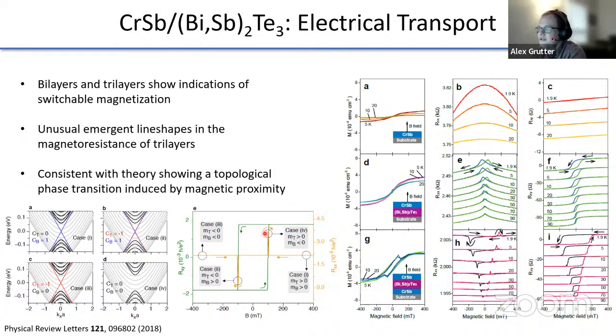We tried hard to carefully look at control measurements, where we look at what the chromium antimonide does on its own, and then compare it to the bilayer. I think the biggest point to make here is that the changes are significant when you start to get these interfaces. But of course, there's been a lot of discussion about why antiferromagnetic proximity effects work in the first place. Why do they exist? And that actually may be why: the spin polarization in chromium antimonide may be super important to these effects. How much the topological surface state leaks into the chromium antimonide, who knows? Unraveling the details of these interfaces is a theoretical study that I very fortunately don't have to do.